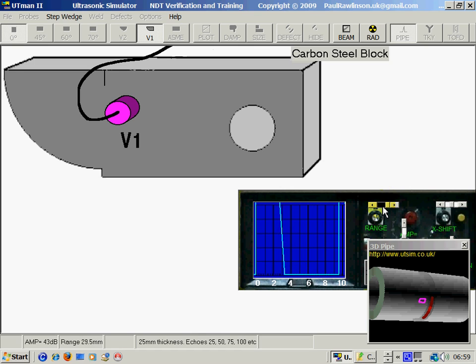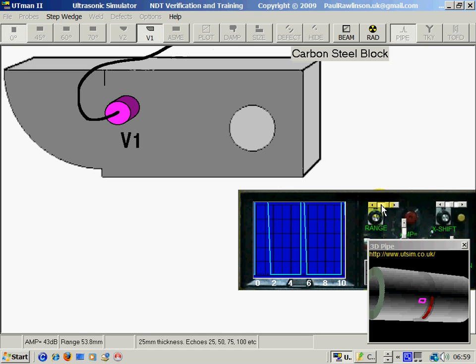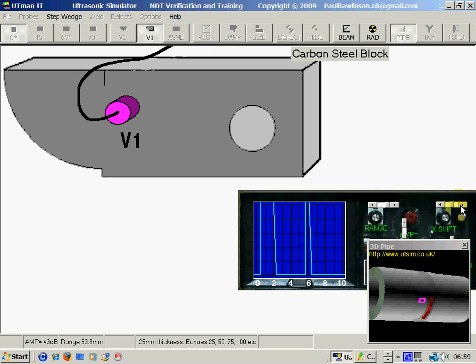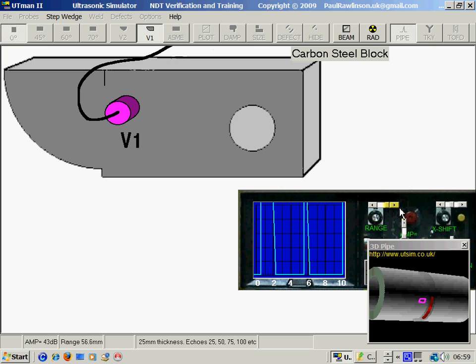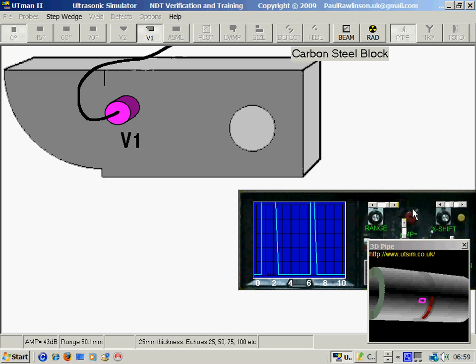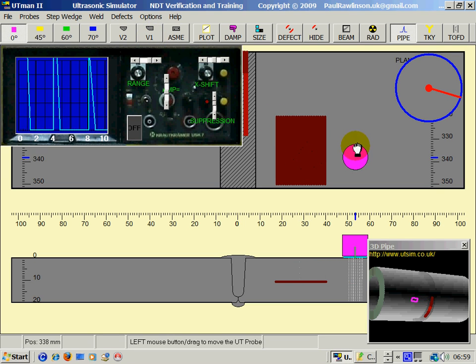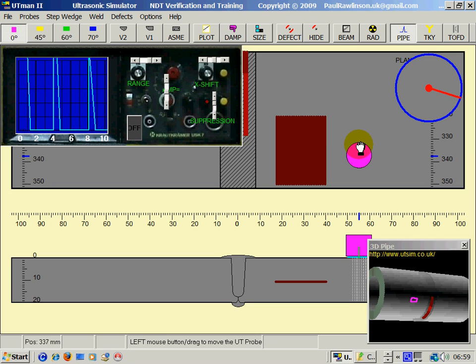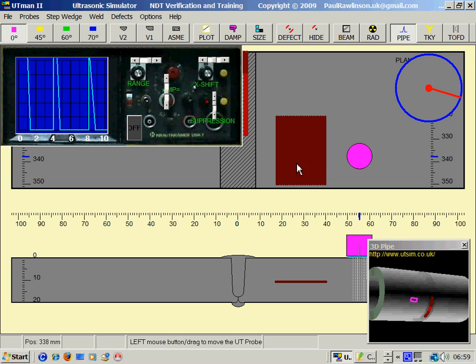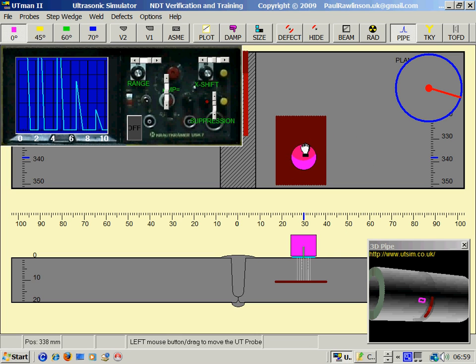I'll get two echoes as we did earlier. So now I've got a range of 50. Go back to the weld - the depth, the thickness of the metal is 25. On this 50 millimeter range for the zero, the depth of the lamination therefore is about 12 millimeters deep.